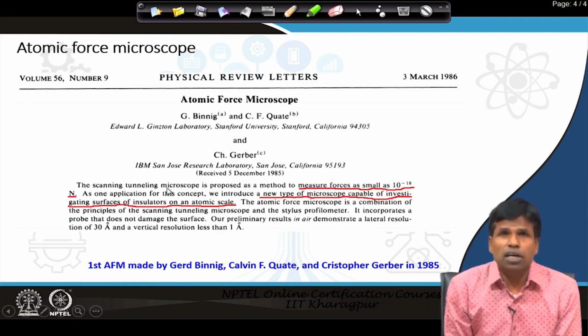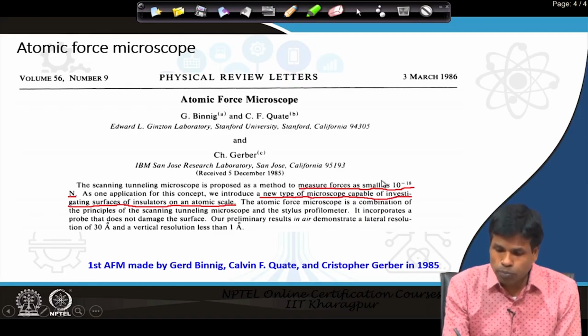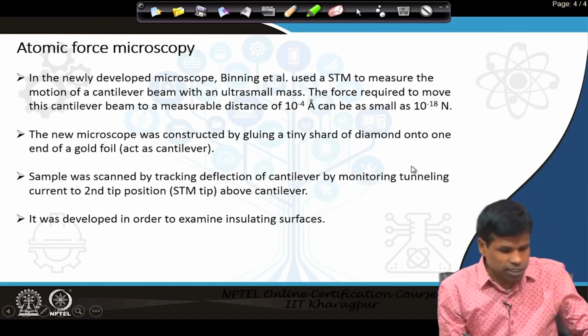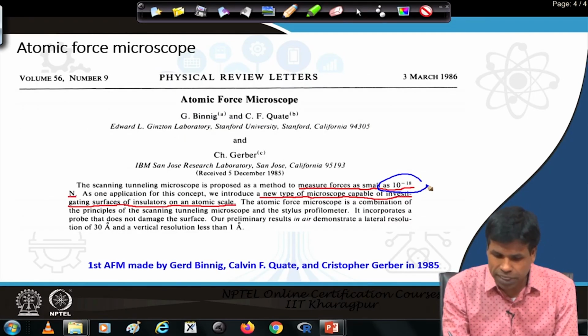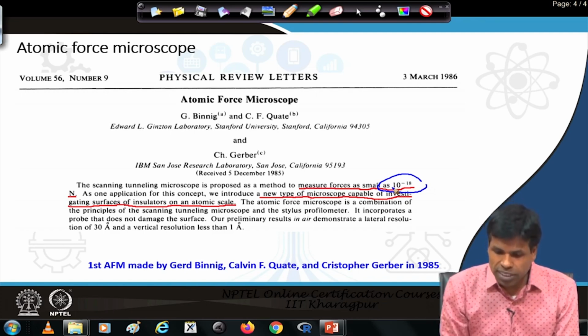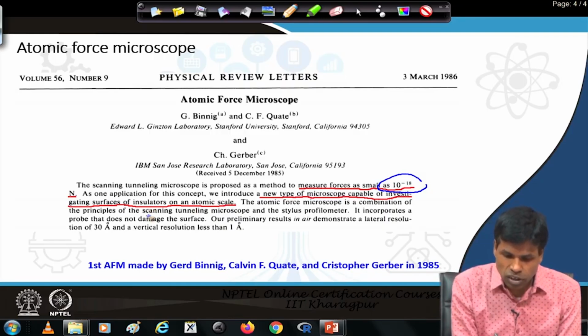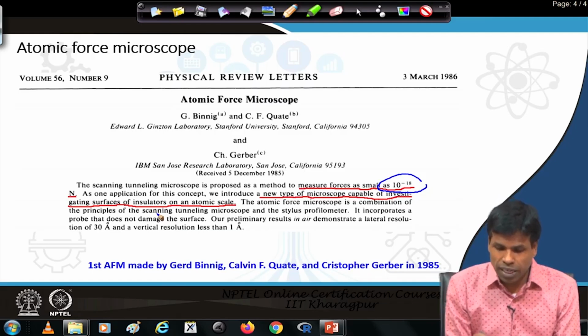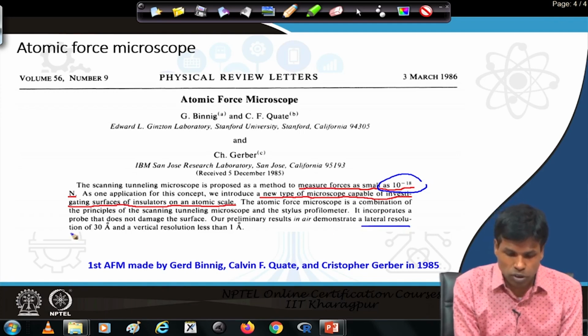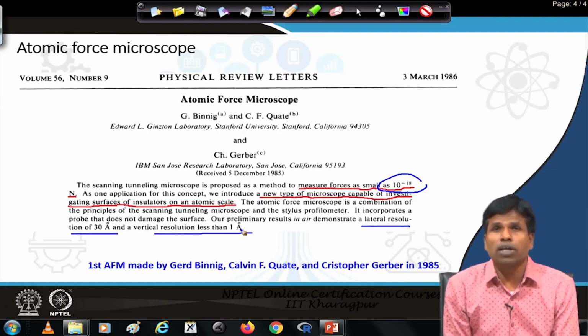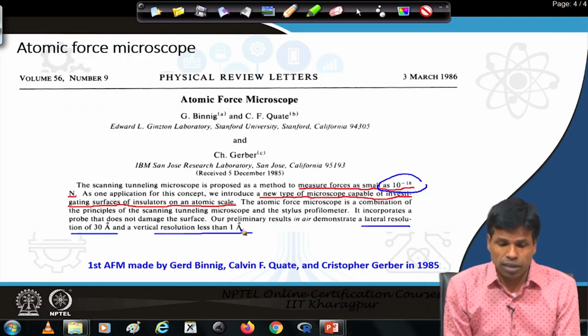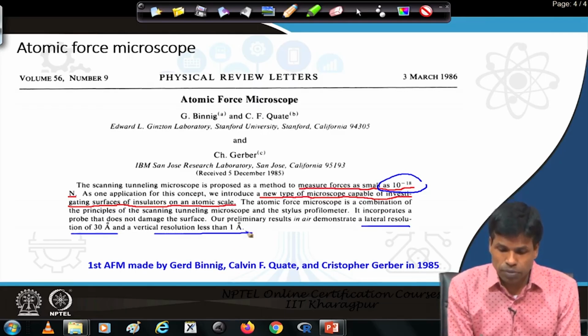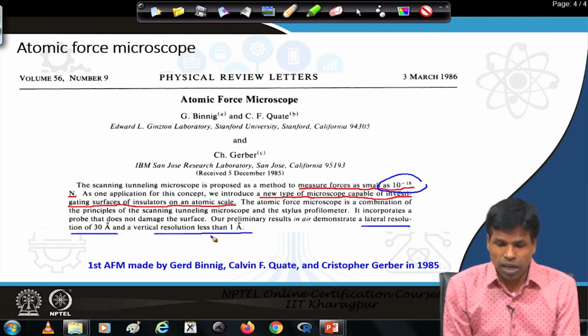So, they used the scanning tunneling microscope again to measure forces as small as 10 to the power minus 18 Newton, and with this microscope they could study the surface of an insulator on an atomic scale. The first microscope could achieve a lateral resolution of approximately 3 nanometers and a vertical resolution of less than 1 angstrom. So, with a modified version of the scanning tunneling microscope, they could achieve a vertical resolution of less than 1 angstrom, and because they measured the forces between the tip and sample, and with that force created the surface topology, they termed it the force microscope or atomic force microscope.